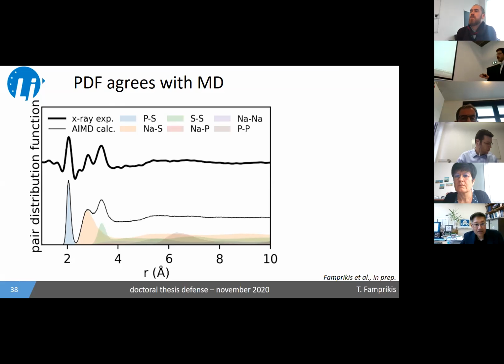And the rest of the, let's say, higher distance peaks are quite flattened. And this can actually be linked to the fact that there's no long range correlations in the material. In other words, one sodium is not limited by what another sodium is doing. One PS4 rotating does not have to match the next one rotating. So everything is moving somehow in a liquid-like sense without regard for what its neighbor is doing.